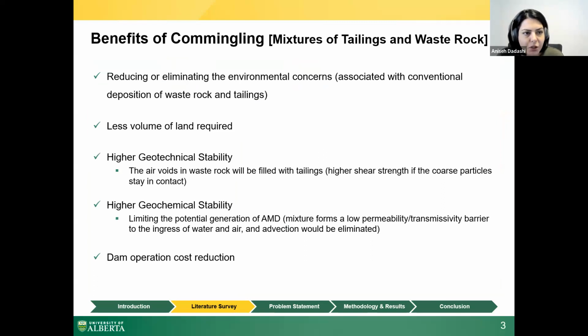The commingled mixture of waste rock and tailing is an integrated approach that can potentially reduce or eliminate the environmental challenges regarding the segregated disposal. If we mix these two wastes together, first of all, less volume of land is required because tailings can be stored in the void space of the waste rock. And if the air voids in the waste rock are filled with tailings, the shear strength of the mixture will increase when the coarse particles stay in contact.